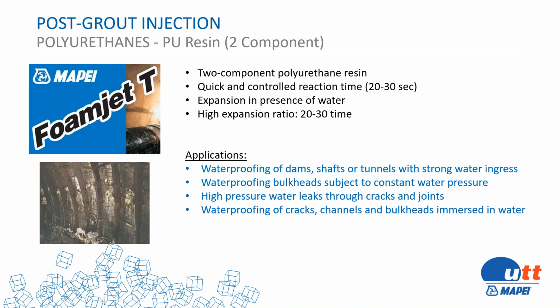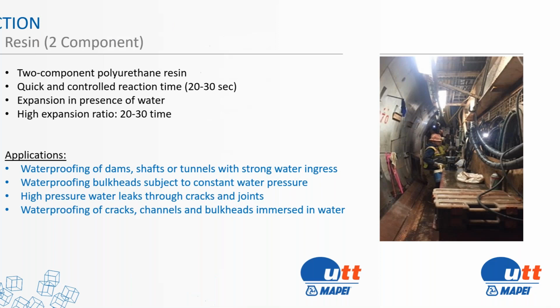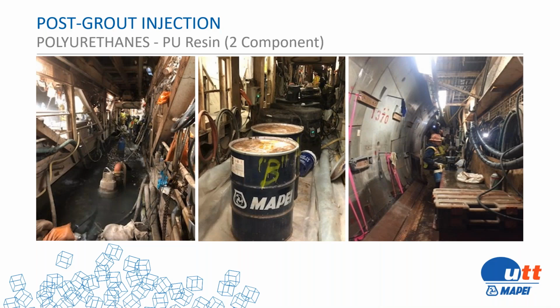The FoamJet family consists of two component polyurethane resins. When I say a two component polyurethane, I'm not talking about what comes in the package. I'm really talking about how it's going to be pumped. It's going to be pumped with a two component pump, and you're going to have component A and component B. You can also accelerate the material to make it go faster. What we like about using the two component materials, especially underground, is that there's no travel time. By putting a catalyst in a one component, it still has to travel through the injection hose. Here we can inject right at the point of the packer, and we can turn off very, very high pressure flows. This is a picture that I took last month in Hartford. You can see on the left that they're pumping out all kinds of water. We have component A in a 55-gallon drum and component B right in front. So we're pumping right out of the containers into the packers.